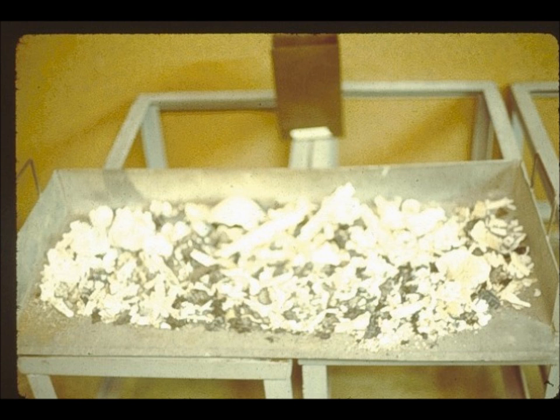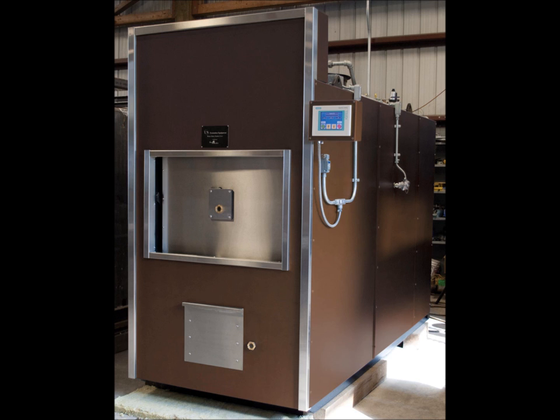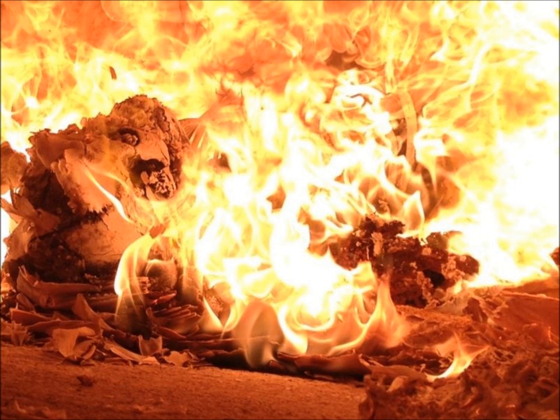Refractory bricks are typically replaced every five years, because thermal fatigue gradually introduces fissures that reduce the insulating strength. For heavy-duty cremators having an inner sacrificial layer of refractory material, cracks, slagging, bulging and dislocation can be seen on this layer shortly after the cremator is put into use. Such cracks and fractures need not be disastrous, as this lining is sacrificial in nature — it may just result in the development of a crack pattern. Those cracked surfaces may be held together and closed by the lining's compressive stresses that develop from thermal expansion when the cremator is heated to operating temperatures. However, the inner sacrificial lining needs to be replaced on a regular basis to offer proper protection to the outer layers.